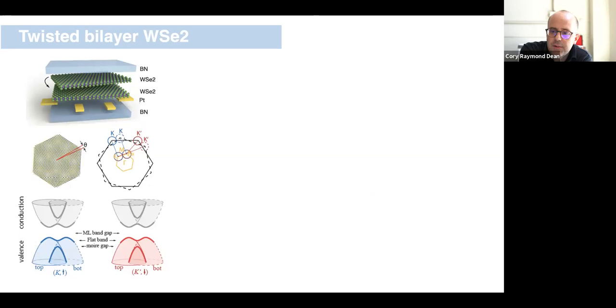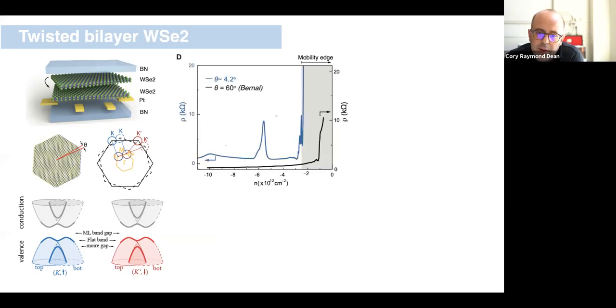What happens in real systems? A little more than a year ago now, we realized this scenario using twisted WSe2, for the reasons that I discussed a moment ago. We fabricated a device at some twist angle, and we measured the transport response. And what do we see? In this device, first of all, we're always operating in the valence band of this material. So I'm always operating at the top of the valence band, which I'm showing schematically here.